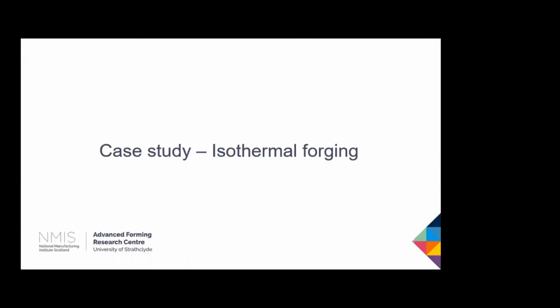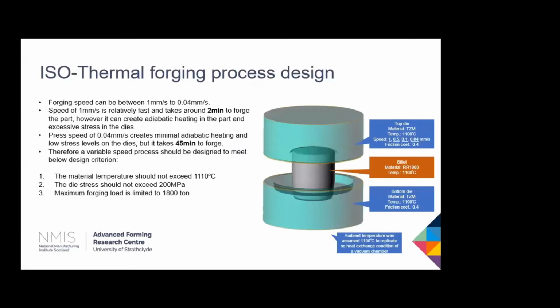Okay, I'm just going to give you a final bit on a case study in isothermal forging. This is just a really interesting example for us. So we know that our scenario can only be between 1 millimetre and 0.04 millimetres per second in terms of speed. If you think about it, if we're going to squash this component here, if we did it at 1 millimetre a second, it would take around 2 minutes. But if we did it at 0.04 millimetres a second, it would take 45 minutes to forge, much slower. Obviously, 45 minutes is not productive.